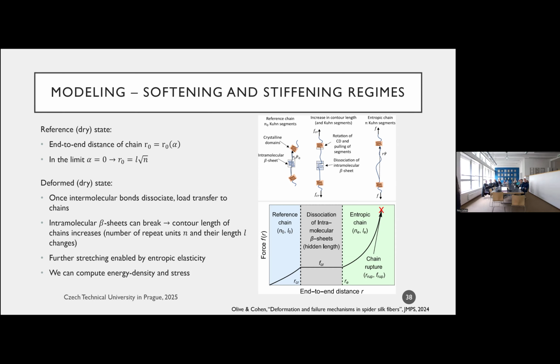So if you look at the force displacement curve for a single chain here, it would look something like this. You would have a certain Langevin response, or the typical response, up to a certain force. At this force, the contour length increases. So you get a jump in the end-to-end distance because the contour length increased. You relieve some of this hidden length. And then you just have entropic stiffening. And so once you do this, again, it's very easy and straightforward to compute the macroscopic response.